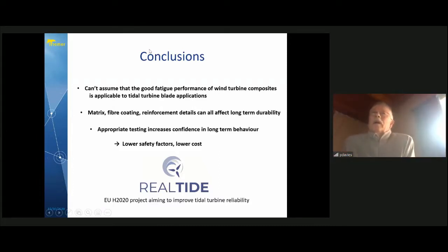Okay. In fact, we had another PhD which finished at the end of last year. It was Antoine Le Guen-Geoffroy, who worked on looking at aging and delamination. And so he did a lot of tests under different modes of loading of the effect of moisture on delaminations and how they propagate. He looked at a carbon epoxy. His application was for composite propellers, but a lot of the questions we're asking for those are very similar to the questions for the tidal turbine blades.